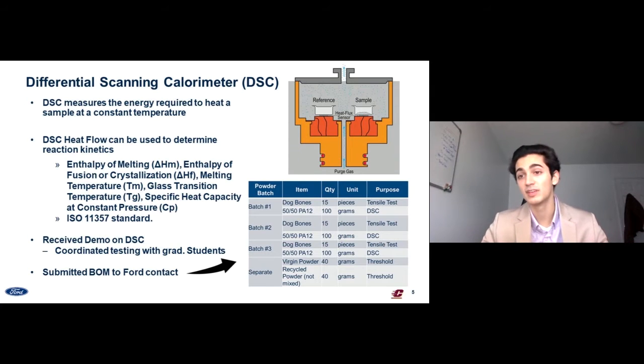And with that difference that we get at the end, the energy difference, we're able to determine the enthalpy of melting, enthalpy of fusion, crystallization, melting temperature point, glass transition temperature point, and a few other things. So that's essentially the data that we're looking for. We'll go into this in more detail in the upcoming slides, but with that data, we're able to determine the quality of the powder.